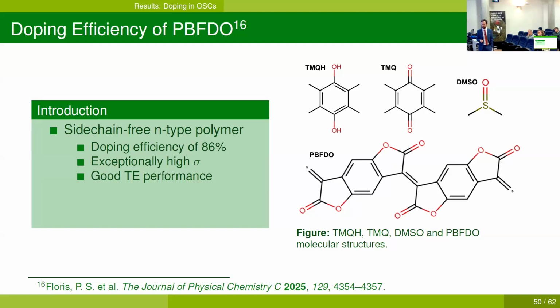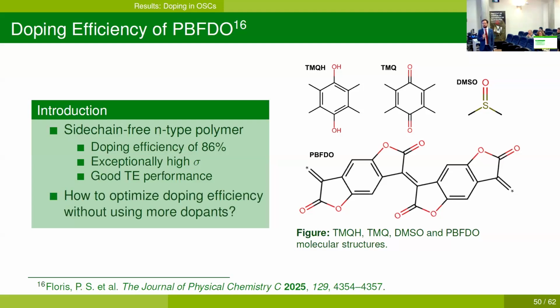We also performed another study, this time on an N-type organic semiconductor called PBFDO, which is depicted here, or polybenzofurandione. This is a sidechain-free N-type polymer. In the literature, it has been found to have a doping efficiency of up to 86%, so almost 9 electrons per 10 monomers, an exceptionally high electrical conductivity of around 2000 Siemens per centimeter, and fairly good thermoelectric performance. So therefore, we decided to study this polymer since it is also very promising. And we wanted to see if there is a way to optimize the doping efficiency without using more dopants.